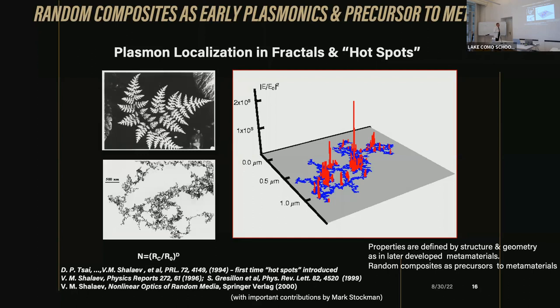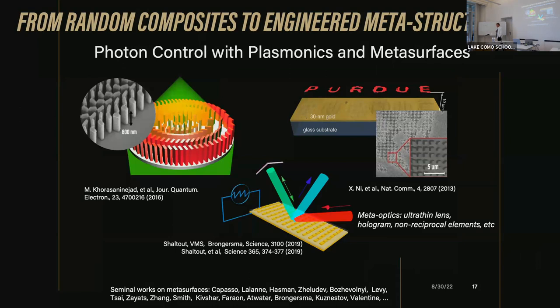But importantly, properties of these structures are defined by structure and geometry rather than material properties, let's say silver, gold, whatever. In that regard, they're very similar to metamaterials that were developed later. With metamaterials, the whole idea is that by controlling shape and geometry, you actually control the optical properties. That was studied first for the case of random composites. So you could argue that they served as a precursor for the field of metamaterials, which by now has a truly spectacular demonstration, particularly when it comes down to the two-dimensional version of metamaterials, or metasurfaces.